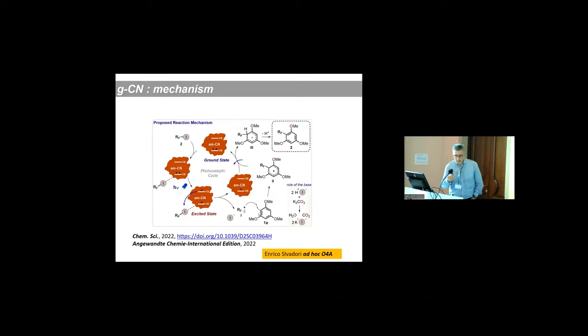It's quite complex. By solid state NMR, by looking at different relaxation times of perfluorinated probe molecules, we proved that the important step is the coordination on the surface of the perfluorinated iodide, the formation of radical species. And we proved that the amorphous material, the most active material, is the one able to absorb more efficiently, to store more efficiently, the perfluorinated iodide.